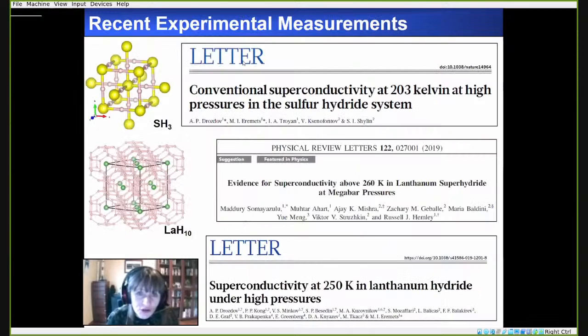So here I show some of the experimental results. What is really fascinating here is that the experiments have been closely integrated with theory. In some cases, for example, this discovery of superconductivity at 203 Kelvin, the experiments and the theory came out more or less at the same time. And in other cases, for example, the discovery of superconductivity in this lanthanum H10 phase, the theoretical calculations actually predicted the target material prior to its synthesis. So this is a true example of materials by design.